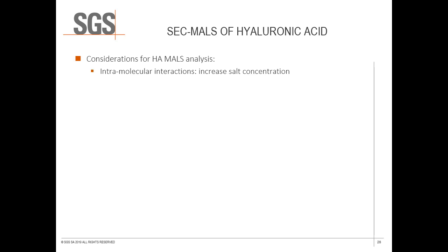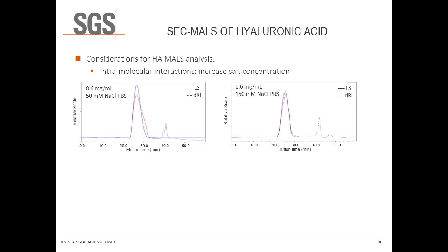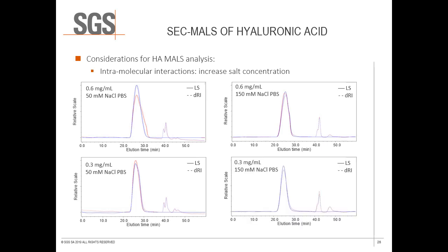Intramolecular interactions occur in hyaluronic acid samples when ionized carboxylic acid groups repel one another and cause the chains to adopt an extended conformation. The resulting high viscosity causes misshapen chromatographic peaks, an effect known as viscous fingering, something that is well known for hyaluronic acid solutions. Higher salt concentrations must be used to shield these electrostatic repulsions between sample molecules. The hyaluronic acid data presented here illustrates a marked improvement of peak shape and reproducibility when the sodium chloride content of the phosphate buffer mobile phase is increased.